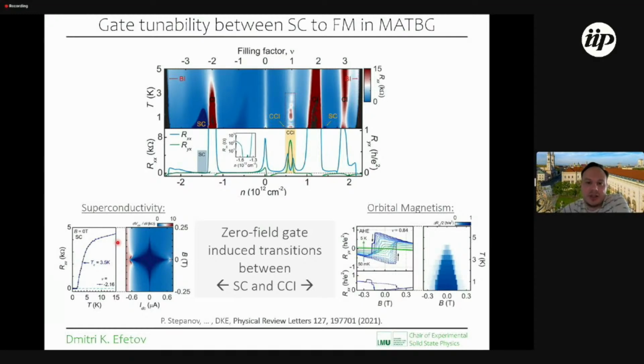And I mentioned to you in the beginning that really these magnetic states, which are shown here, reside basically at one filling factor, at one electron per unit cell. However, if you just change the density a little bit and you move in that direction, you find a superconducting state. So in principle, just by electrostatically changing the voltage on your gate, you can induce transitions between superconductivity and magnetism. And so we really liked to create devices that hybridize these states with one another.